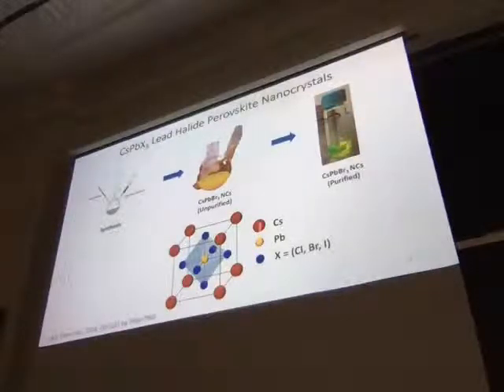And this figure just shows the general crystal structure of these materials. The crystal structure is called perovskite. It's a type of mineral that people have used for a while. This is the general mineral structure where the lead atom is coordinated to halide ions octahedrally, so lead in the middle and then you have, in this case, bromine; we have other halides as well. And these big red ones are just space fillers to make the crystal structure stable. So that's what cesium does.